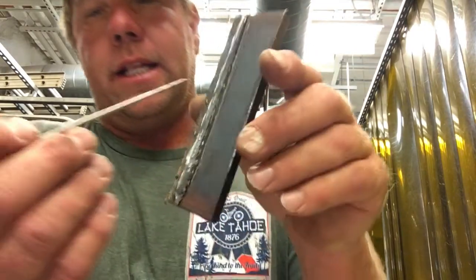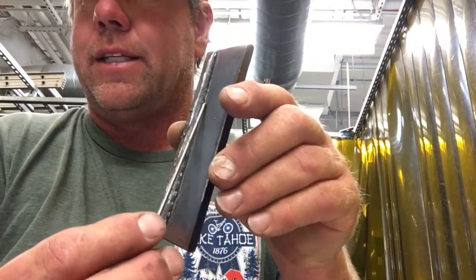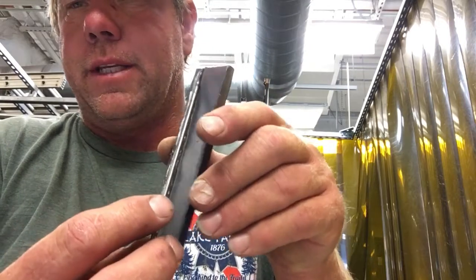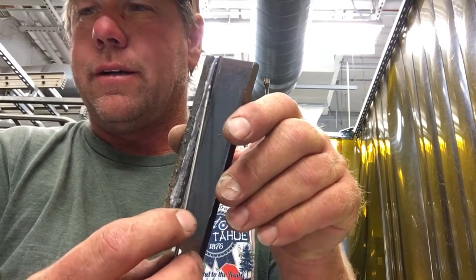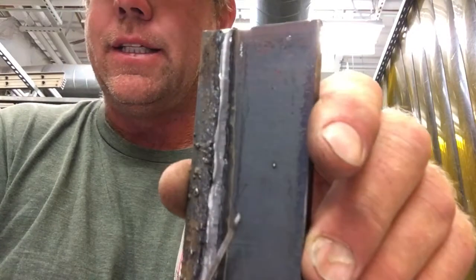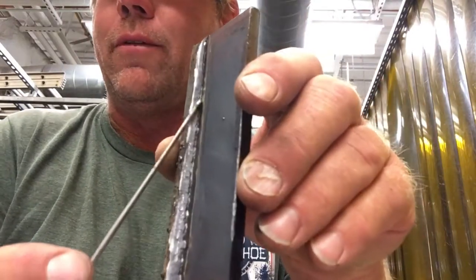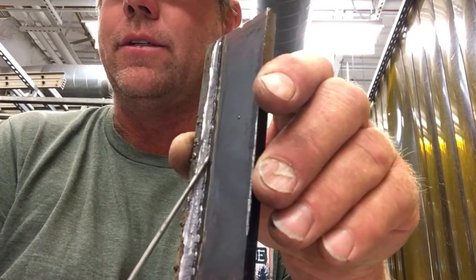Single pass that I broke. I believe I have a couple of those. Yeah. So common. Again, let's look at that little slag inclusion. Now I said slag twice now, but with a different qualifier. This is a slag inclusion. It is included in the weld. There's some more of it right there. That's slag inclusion. And this is actually due to the fact that this lower plate's a heat sink, and that's what draws it over there.